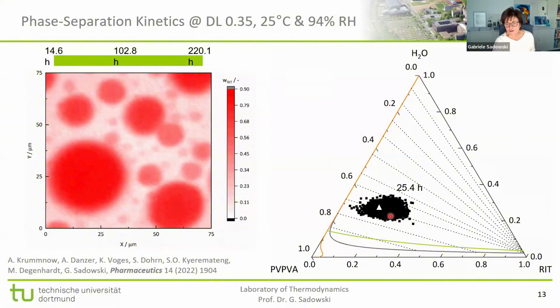And this is our Raman measurement. So this is the starting point. What we did is we had a drug load sample of 35%. So we started down here, at 35. And then we put the tablet into water. So that means it will absorb water. And depending on the RH and temperature, it will absorb a certain amount of water. And that's a triangle. The triangle is the amount of water in the system PVPVA ritonavir that the sample would have in equilibrium. And then what you see is the black squares.